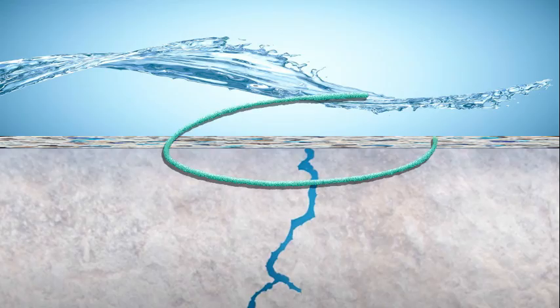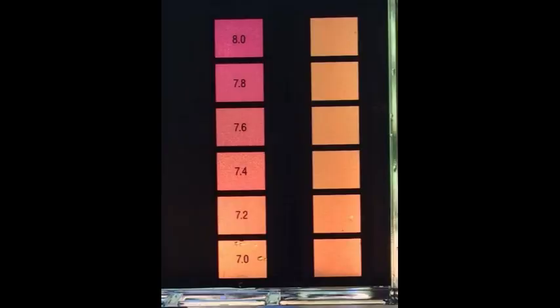Before you see calcium nodules, the surface has micro cracks — little pinholes — and when water gets into these cracks, it creates a tunnel beneath the surface. The small void between the surface and gunite fills with water, which then transports the soluble salt products and calcium to the surface. That's where we see the calcium nodules form.